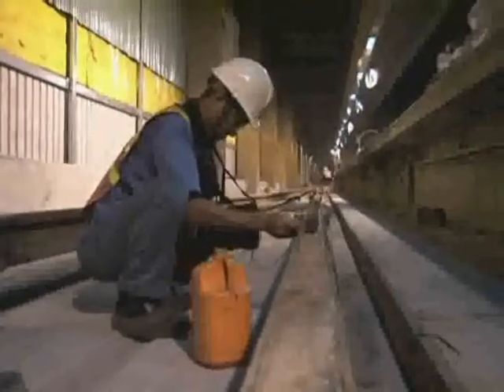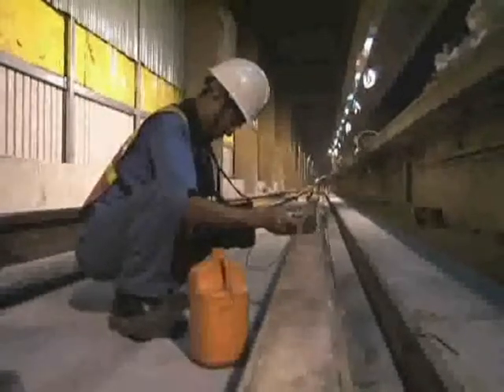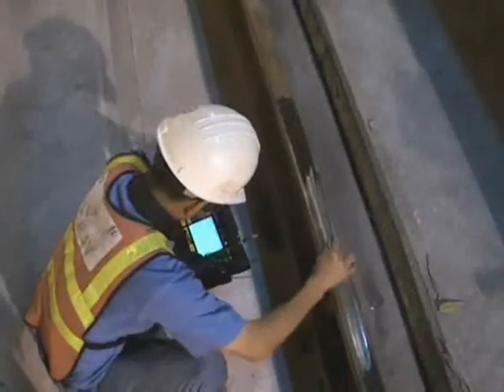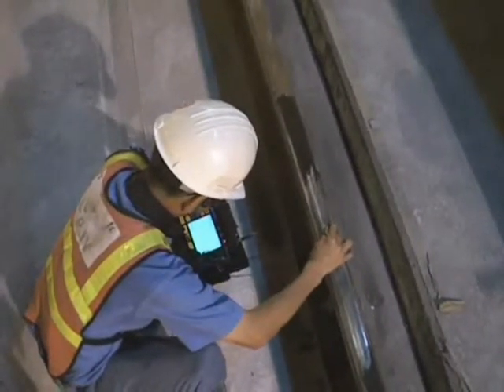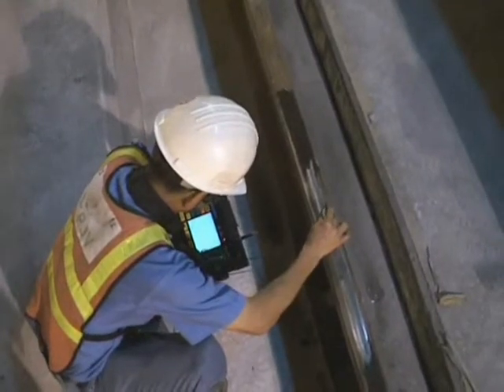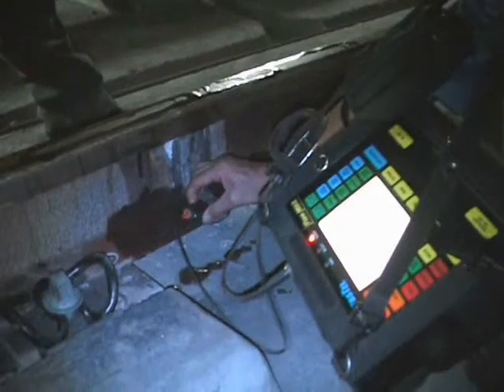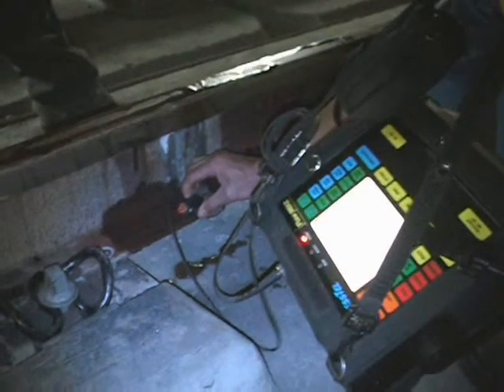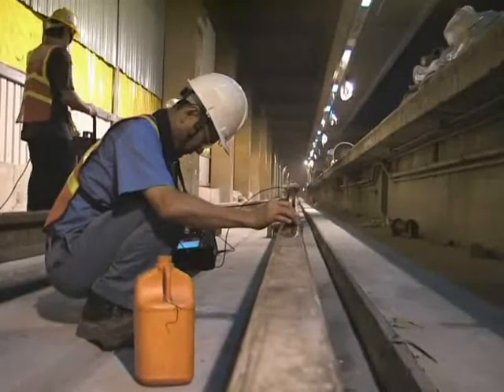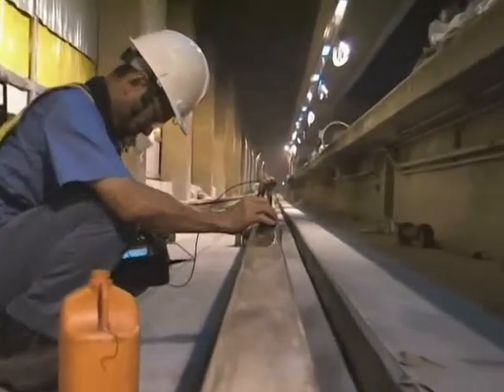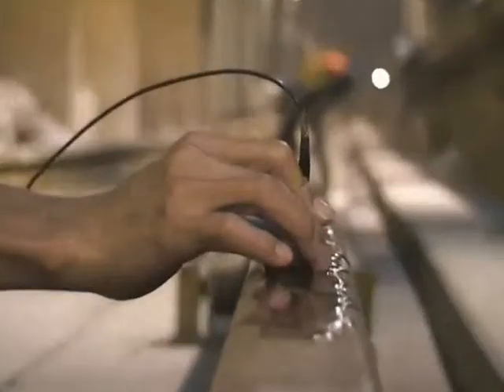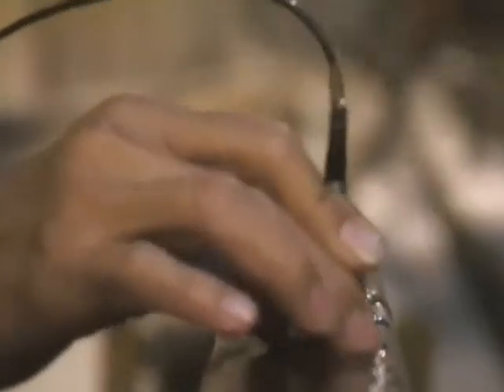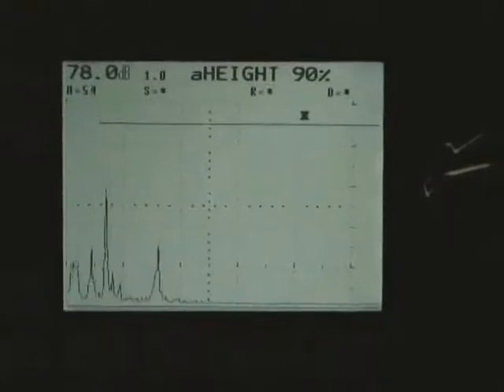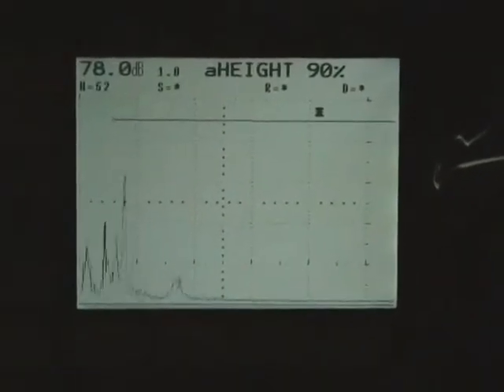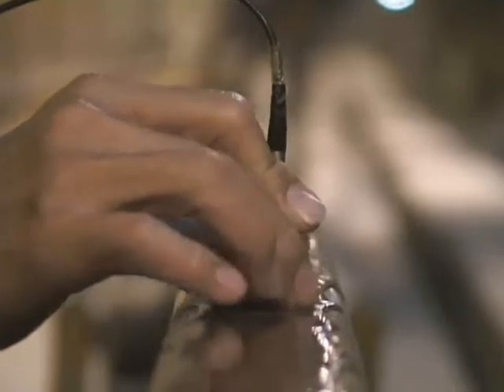Every rail joint on the project, over 2,500 flash butt welds and almost 1,000 thermit welds, needed to be ultrasonically examined for flaws and defects. This involved a series of examinations with a test rig that sends and receives ultrasonic sound waves, bouncing them along the rail surface. If the receiver does not detect the transmitted wave, it is likely that some type of defect has occurred in the rail. These can take the form of cavities, cracks, or foreign bodies, such as sand from the clay moulds.